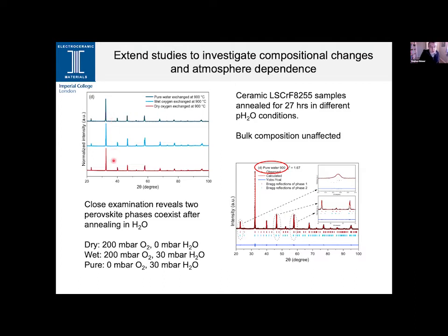Interestingly, the observation is that all of those are stable after that 27 hours anneal, so the bulk composition is unaffected. But closer examination of the data by Rietveld analysis of high quality structural data, particularly of the reducing samples, the pure water environment, highlights that there are in fact splittings of the main perovskite reflections. The insets here highlight very nicely those splitting features, which indicates that there are two structurally related perovskites that are coexisting. And that only occurs after that anneal atmosphere.